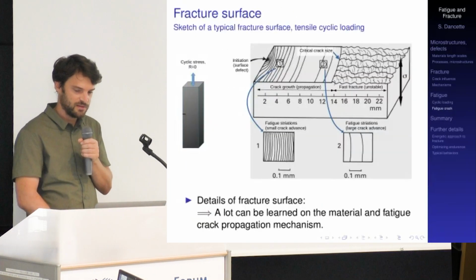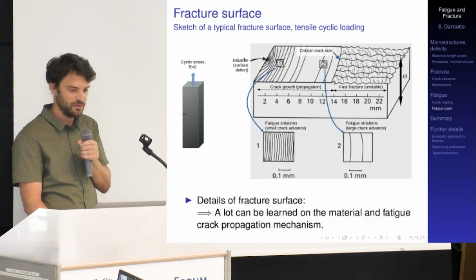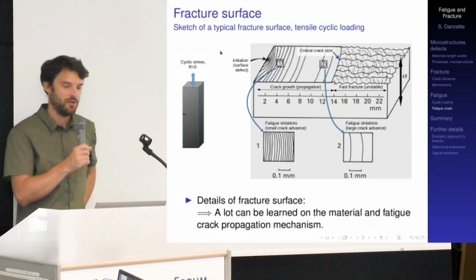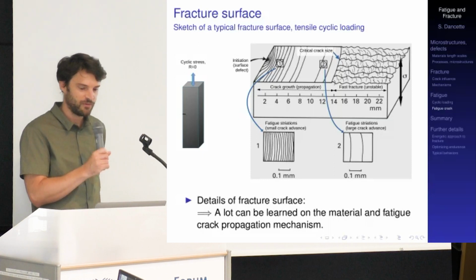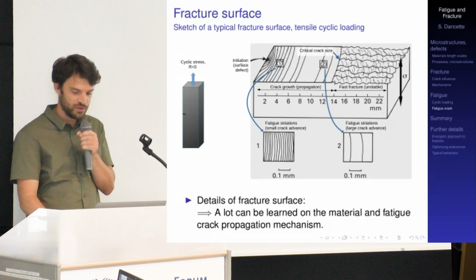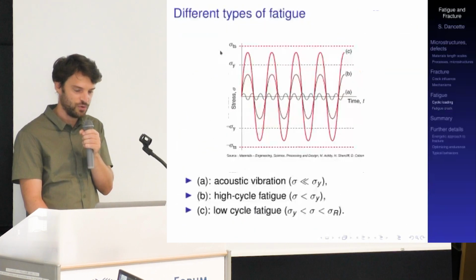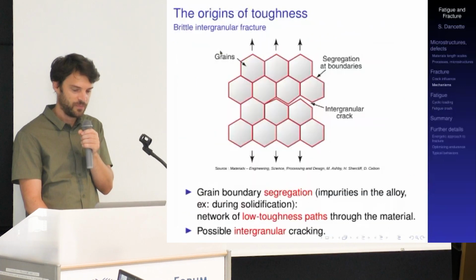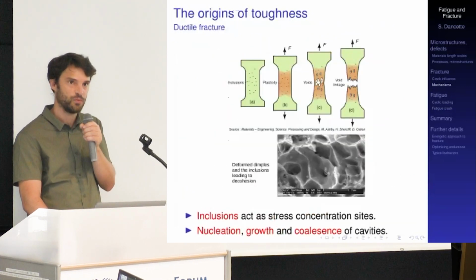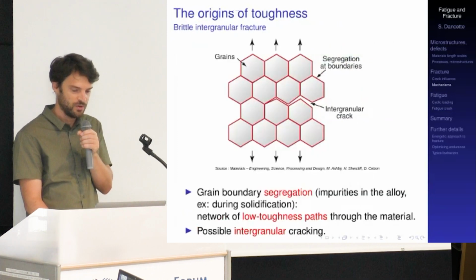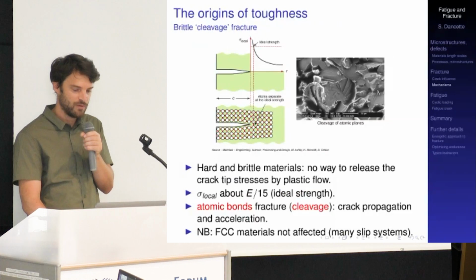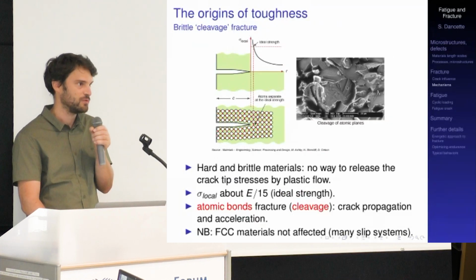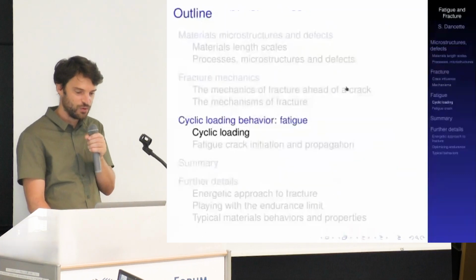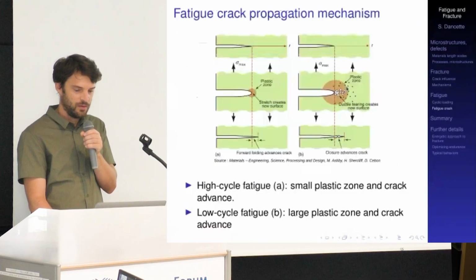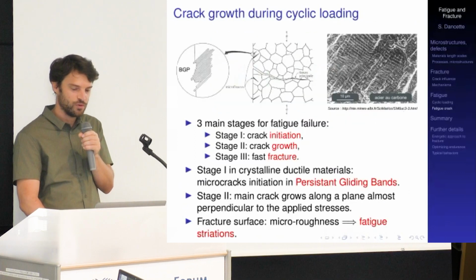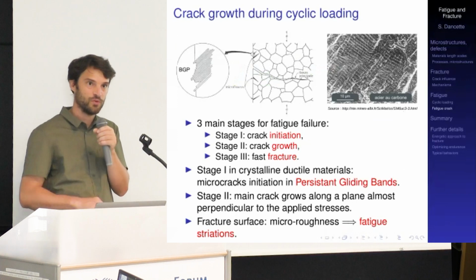So this is, I think, the last slide. Just to tell you that it is very common in fracture investigation, and especially fatigue fracture, to look at fracture surfaces. We already discussed fracture surfaces in the case of ductile fracture behavior, with the dimples that we can see using scanning electron microscopes. We can also retrieve the features of cleavage fracture just by looking at the fracture surfaces in a scanning electron microscope. But if we do the same in the case of fatigue, then, if we look close enough, we can distinguish these fatigue striations, showing how fast the crack was advancing during